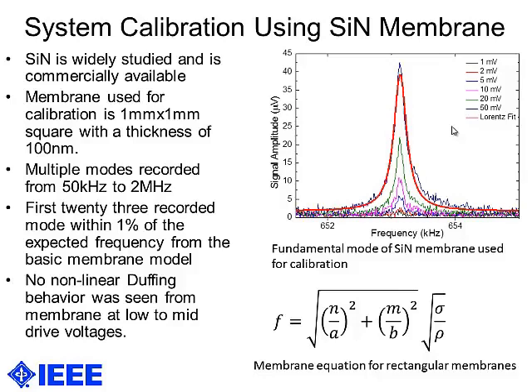The square membrane equation is based on the mode number, which is N and M, the side lengths, A and B, stress, and density. Comparing it to this equation, we found that all of the modes fell within the expected frequency location to within 1% of the expected. We also didn't see any nonlinear Duffing behavior in the lower drive voltages for the silicon nitride membrane.